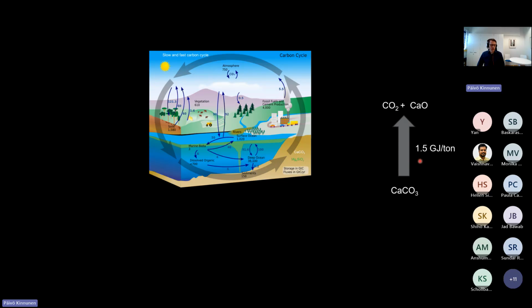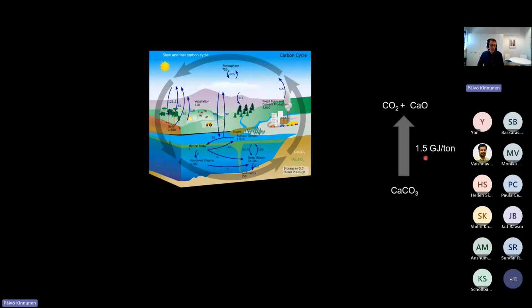And so the amount of energy needed is about, in theory, 1.5 gigajoules per ton. Which is little. So if you compare that, with the same amount of energy, you could take 1 ton of water and heat it up to around 250 degrees. And with that energy, you can actually produce the cement. So it's very, very little in terms of energy, and so this is what we're up against. If we want to come up with alternative binders, it needs to be better pretty much in every way compared to this. So especially in terms of energy, it needs to be at least comparable. And of course, in a real system, it's something like twice this. So 3 gigajoules per ton is something. Let's say 4 is what the current industrial standard is.